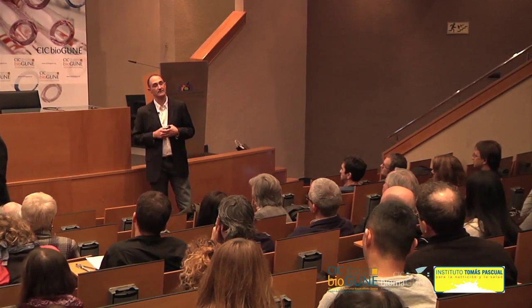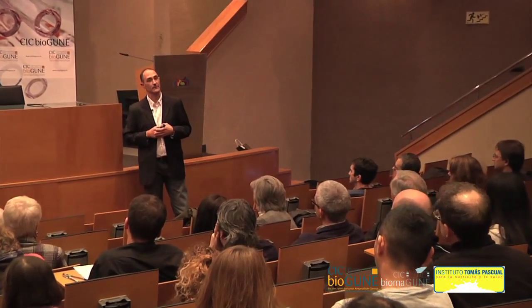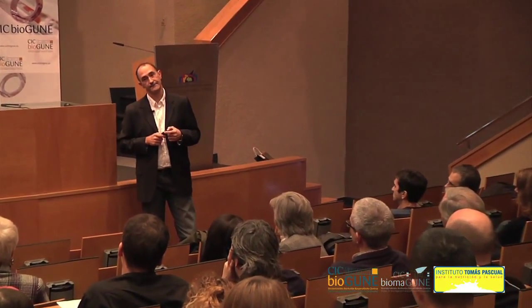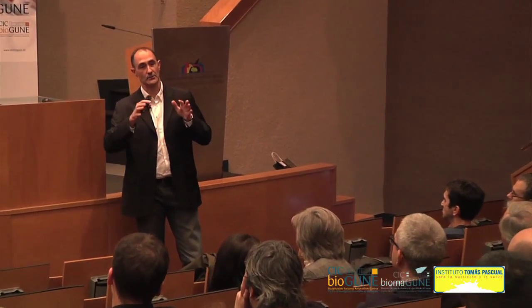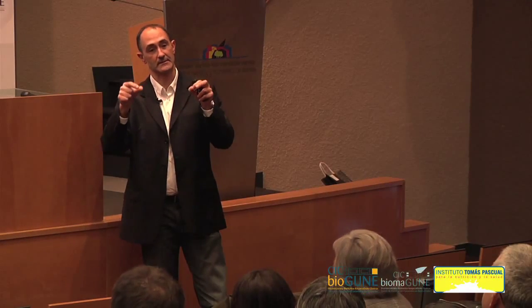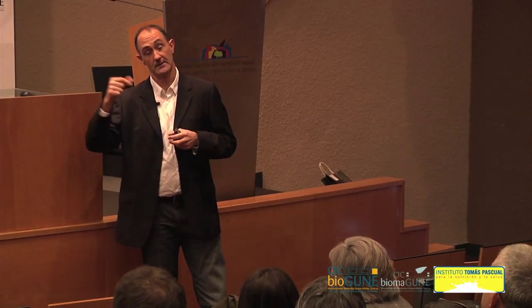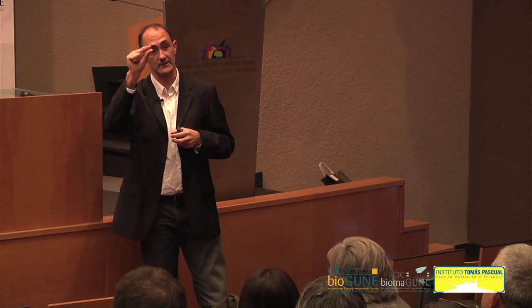Yes, this is a little bit unexplored so far, but I think that there is a lot of potential. It depends a little bit how far you want to go. I have not shown very much of the plasmonic characterization of particles with different morphologies. But in fact, you can fabricate the particles in such a way that certain parts of the particles are a lot more active than others. For example, in the nanostars, you see that this electric field is focalized on the tip. At the middle part, there is basically nothing. So you could also foresee that you can do chemical reactions more specifically at the tips.